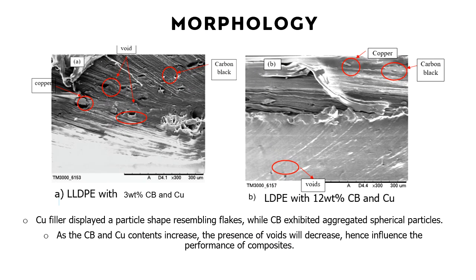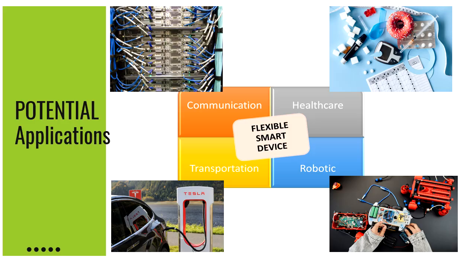We can see that the copper filler displayed a particle shape resembling flakes, while carbon black exhibited aggregated spherical particles. And we found that as the carbon black and the copper content increase, the presence of voids will decrease and influence the performance of the composites.